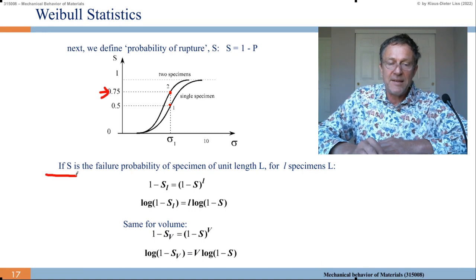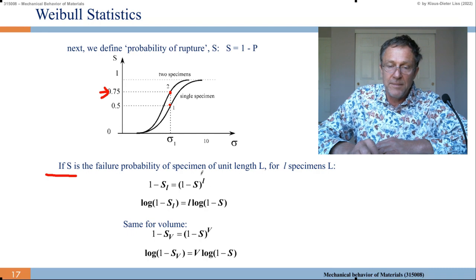So if S is the failure probability of a specimen of unit length L, then for l specimens of length L, 1 minus S_L equals (1 minus S) to the L. So I have a unit length. And I now can take the logarithm. Logarithm of 1 minus S_L equals L times log of 1 minus S. And the same we can write down for the volume. So we can argue with L, or we can argue with the volume.